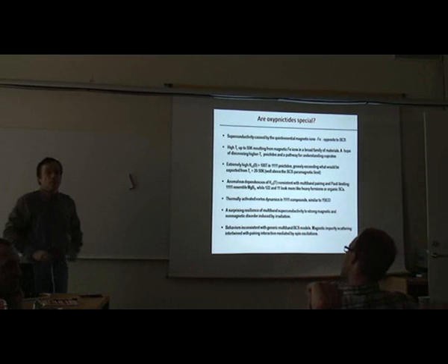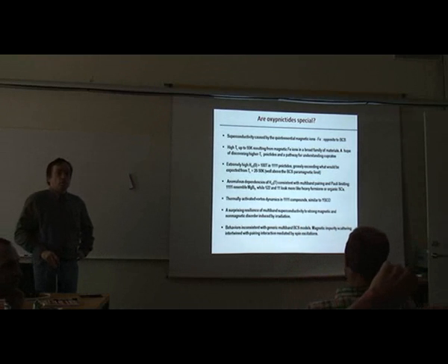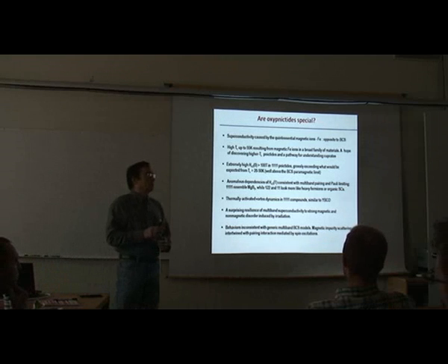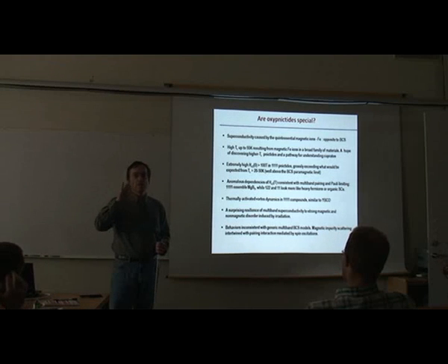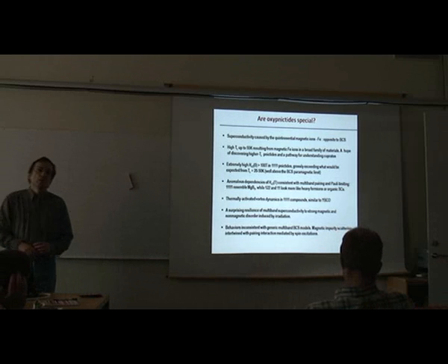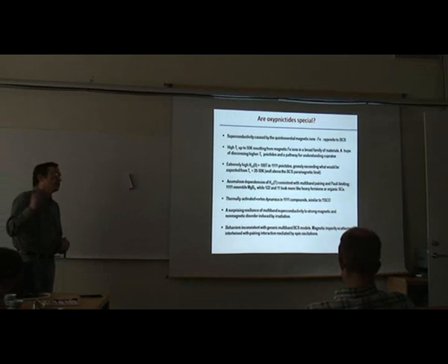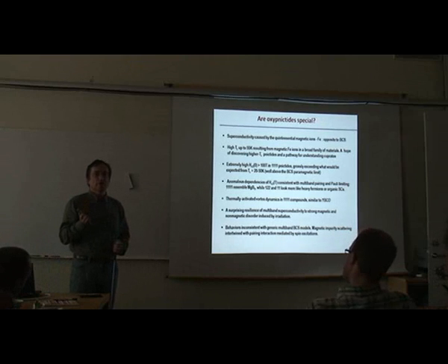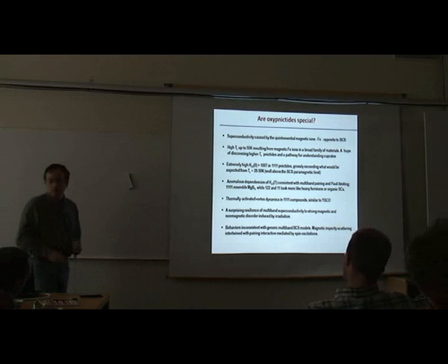In principle, you can measure the magnetic susceptibility and get a better estimate for this Zeeman limit from that. Well, in fact, you actually don't even need to measure magnetic susceptibility. You simply equate the Zeeman energy to the gap. Yeah, but that gives you an idea of the magnetic energy associated just from the susceptibility, and then you can relate that to the condensation energy, and that gives you a better feel, perhaps. That's true, but if you actually take into account susceptibility, that gives you even lower energy because susceptibility is pretty high here. This has a lot of paramagnetic ions in it.